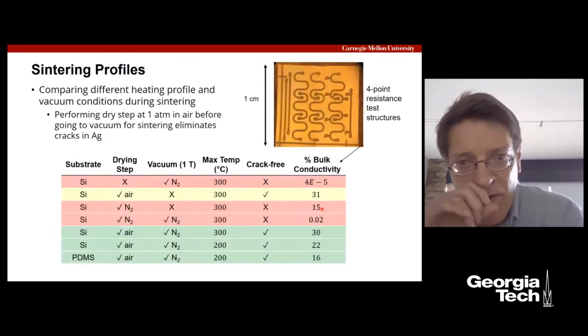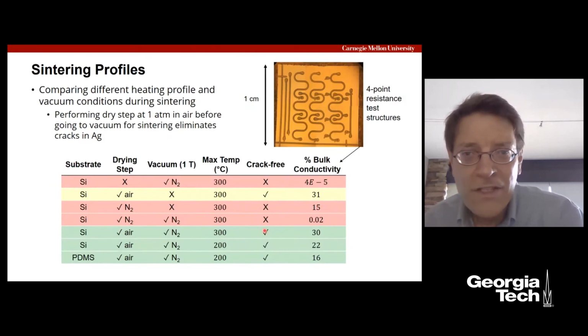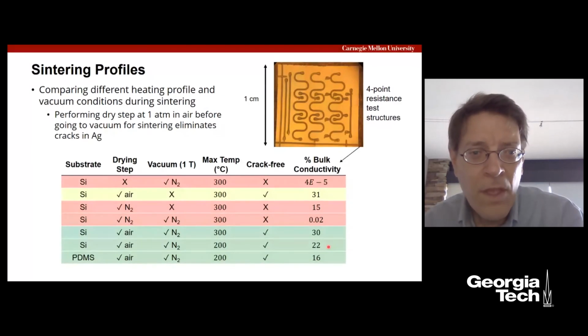And so we tried a bunch of profiles. Bottom line, using 4-point resistance test structures to look at the conductivity, what we found was that on the red we're getting cracks, right? So that's bad. In some cases we were able to do the test structures and see what the conductivity of the wiring was, but the cracks are a no-go, and that was happening because we were either not in air or not doing the drying step.